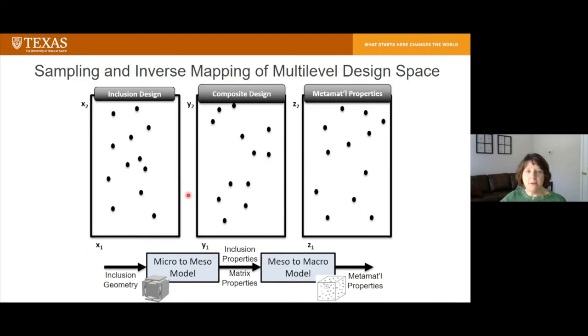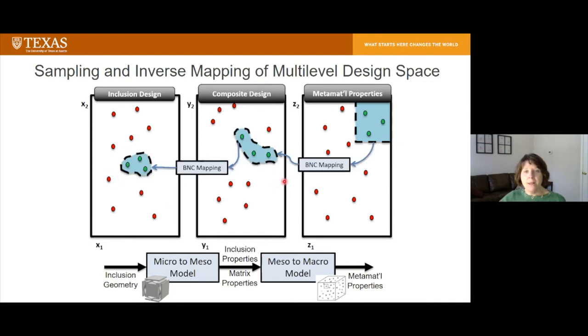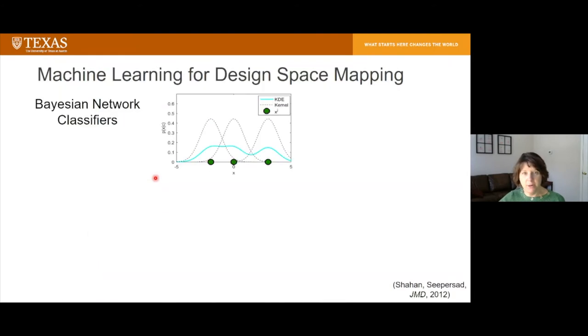So what we do is we take these models and we sample. And so each of these little polka dots here is meant to abstractly represent the fact that we're sampling. We're trying different geometries, seeing what properties they give us, combining those properties of the inclusion with matrix design variables, and then seeing what kind of metamaterial properties we get. We're targeting certain properties. We want high stiffness, high loss. And so then we classify those as high performance. And we can trace those back to the different design variables that gave us that performance. One of the things we're doing is using machine learning classifiers to map those regions so that we can generalize about where good designs lie versus poor designs.